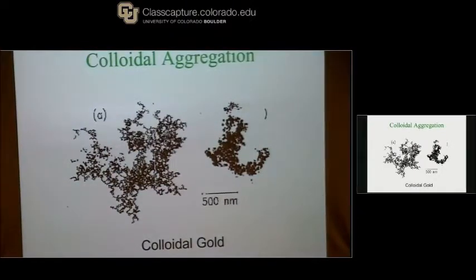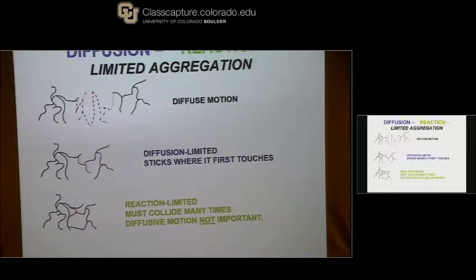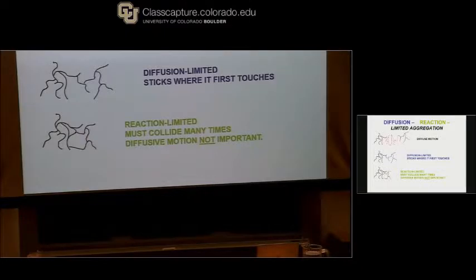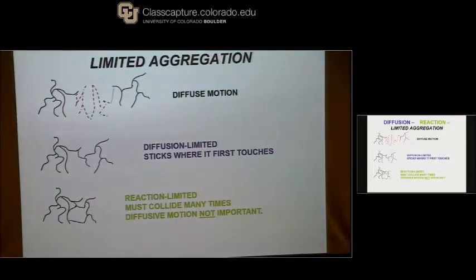But if you do this and you measure the fractal dimension, what do you immediately know by the fact that you can't see through it? Higher by how much? More than 2, exactly. It has to be greater than 2, right? Because you're filling a two-dimensional space. So if you're filling a two-dimensional space with something fractal, it has to be greater than 2. And this is greater than 2. This is about 2.1.